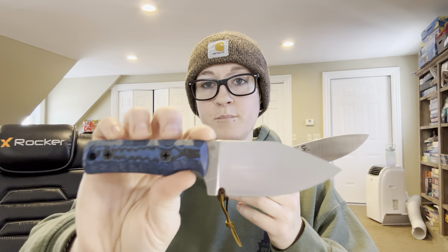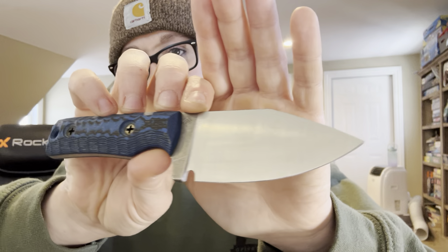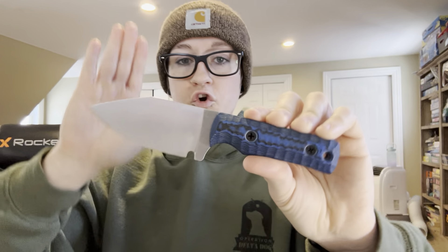This knife is one of my best performers out of my entire collection, hands down — and I have a lot of knives. It's tied with my BGM Knives Mini Spade, full flat ground in MagnaCut. That one was 62.5 to 63. I had a little bit of trouble with it at first, but I realized the edge was convexed because that's how John did his edges. Once I got rid of the convex, it instantly turned into one of my best performing knives in terms of edge retention. The toughness is still there. High hardness MagnaCut is, in terms of the stainless world, king in my head.